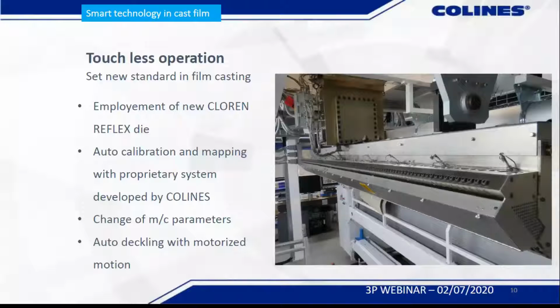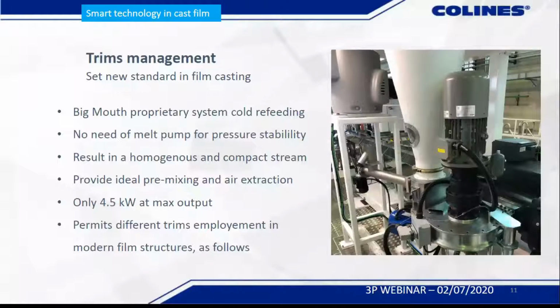The novelty that we have been using since 2009 is our big mouth system, which basically is a rotary channel feeder. It's not a vertical hopper. This basically results in a very homogeneous and compact stream of the fluff mixed with granules. So it's an ideal unit for pre-mixing, and it grants total air extraction because the mix is getting fed into the extruder. It grants also very low consumption at max output, for example, on a 3-meter stretch machine or 3.2 meter CPP MOPP lines. It consumes only 4.5 kilowatt.